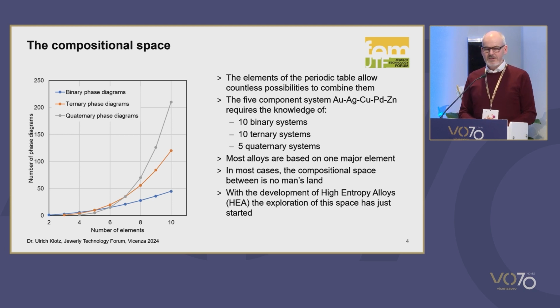Now, if you look at a typical 5-component system, this is something we're using: gold, silver, copper, palladium, zinc, a typical selection of elements that we're using in white gold. We see that we already have to know 10 binary systems, 10 ternary systems, and 5 quaternary systems. So this is a huge space, and we don't know this space. So we only know the regions around one corner, let's say the gold-rich corner, the silver-rich corner, the copper-rich corner, the palladium-rich corner, but you're aware that a gold alloy is very different from a copper alloy and from a palladium alloy. So actually we know very little about the space in between. And so it's actually a no man's land that